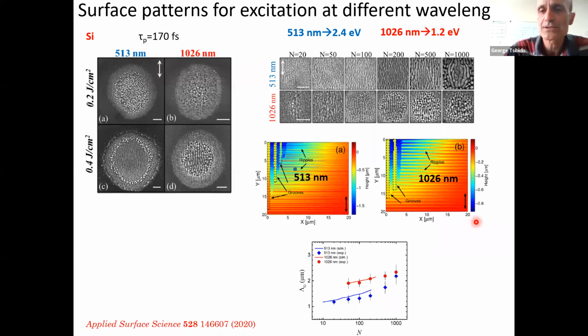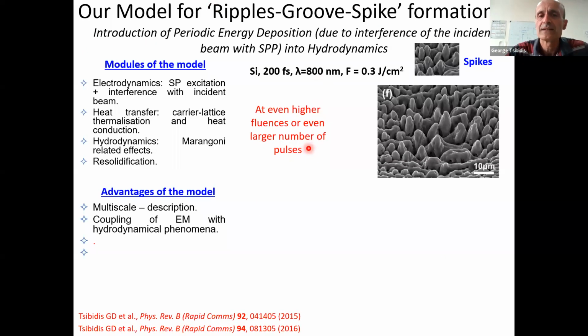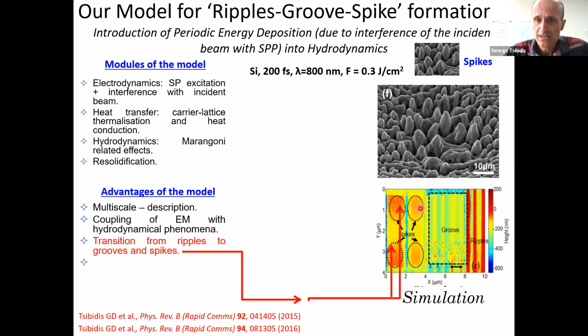And of course, this is not the case only for photon energies related to 800 nanometers that we used in the previous transparencies, but also if we use higher photon energies or smaller photon energies, again, we are able to produce both types of structures on top of silicon. And of course, we can increase even further the fluence, and even the number of pulses, the energy dose, and in that case, we end up with protrusions, so some more complex structures like this.